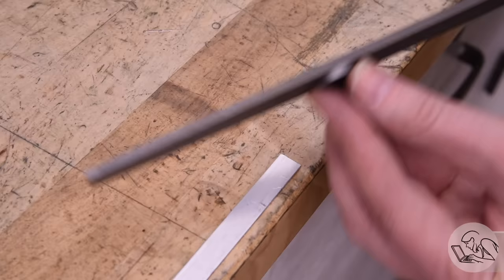Regardless of your tempering method, if you keep going, apply more heat past that yellow brown color, then you get into these purples and blues. And this is a softer temper. This has many uses as well, so it's good to know what this looks like. Let's get the punch on this and let's see what it looks like. Here you can see we're somewhere in the 45 to 50 range now. So this is noticeably softer than the yellow brown, but this is going to be tougher and more flexible than the yellow brown part is.